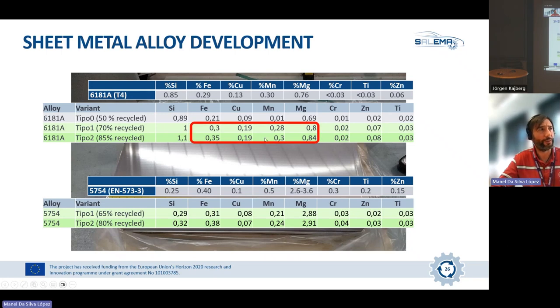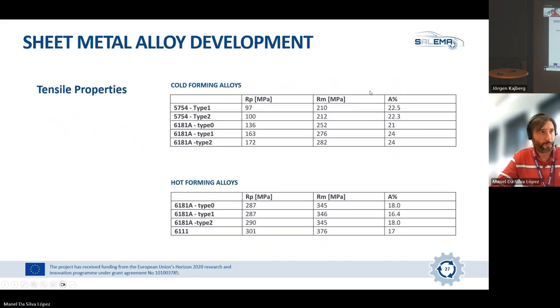In the 6181, in order to reach this level of recycled content, it was necessary to increase the amount of impurities present, iron, copper, and manganese mainly. We also increased magnesium and silicon in order to compensate, and some zinc was also increased. In 5754, it was possible to produce with a very similar composition, just some higher iron was required. The mechanical properties in the tensile test were very similar. So increasing the level of impurities didn't really affect the mechanical properties, even if we were cold forming or hot forming these alloys.